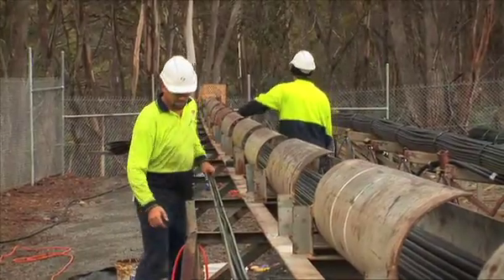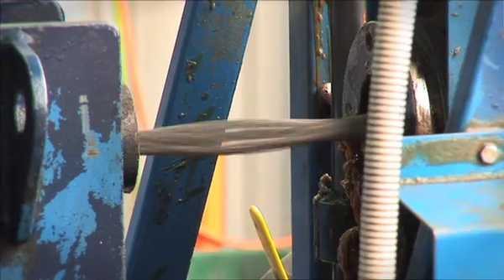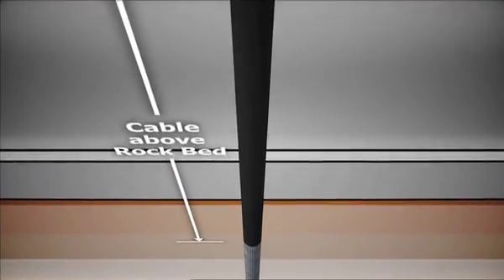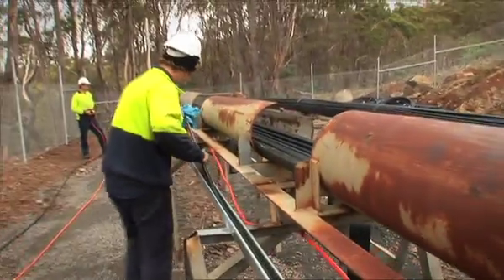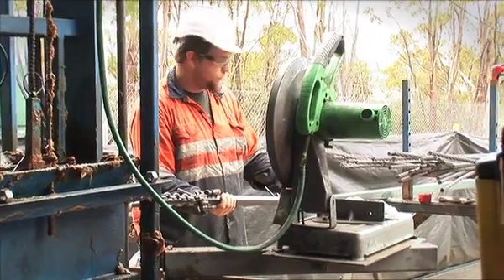The cable manufacturing process starts with a three-tonne coil of strand. It is heated up, then dragged through a pushing machine which separates the seven wires, pushes it through a grease bar which fully coats the strand, reforms the cable, and pushes it into a plastic tube. That forms the free-length part of the anchor, from above the rock up to the top of the dam. This is repeated numerous times until we get 91 strands into one bundle. Each of the 91 strands is individually grease-filled, so that there's full exclusion of any air or water for the life of the anchor.